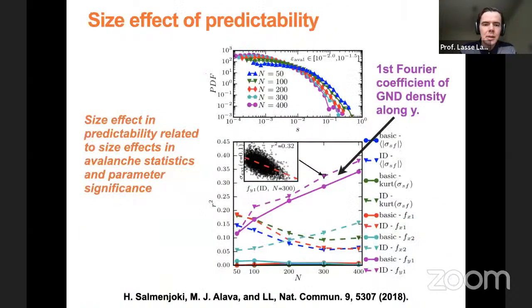So that would be that. Then you can also look at the size effect. One thing is, of course, that you have these avalanches, which themselves exhibit a size effect. As we saw in the very first slides, if you have a larger system, your stress strain curves tend to be more smooth. So the deformation avalanches are smaller. And then this could make it somehow easier for the model to predict what actually happened, because your avalanches, these stochastic, hard to predict events, are smaller. But then you can also look at the linear correlations between the stress at the given strain and various features that we fed to these machine learning models.